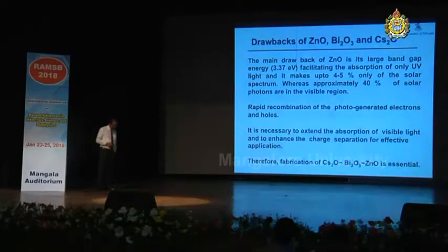Well, we have been talking a lot about these metal oxides, but there are some setbacks with respect to these metal oxides. The main drawback with zinc oxide is its large band gap energy, 3.37 electron volts, facilitating the absorption of only UV light, and it makes up only about 4-5% of the solar spectrum, whereas the remaining 40% of the solar photons are in the visible range,